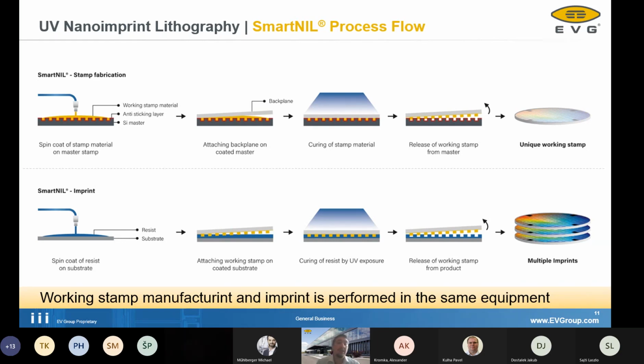So we don't work with PDMS anymore, because it's not efficient enough for high volume. It takes several hours to cure in good quality. So we rather tend to use UV curing materials we developed on our own. And then you have this unique working stamp. And when you have this working stamp, you can go to the production process.